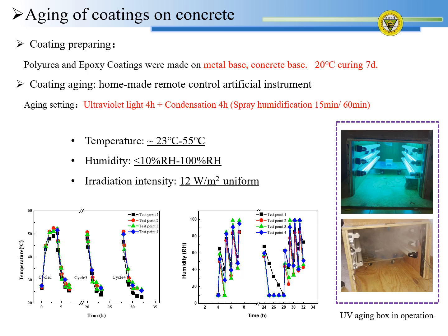And in the condensation part, we use a sprayer to cool down. In the irradiation step, the temperature can go up to 55 degrees and the relative humidity would decrease below 10%. Then, in the condensation step, the temperature goes back to room temperature and the relative humidity is close to saturation.